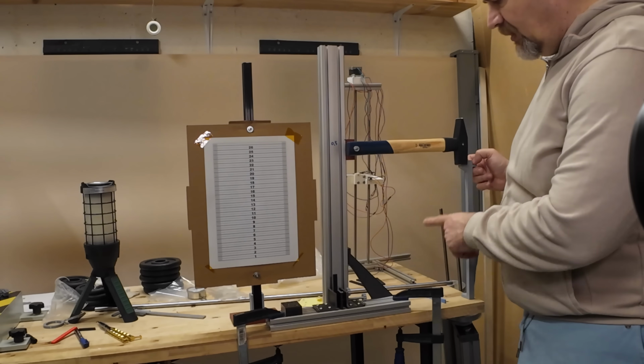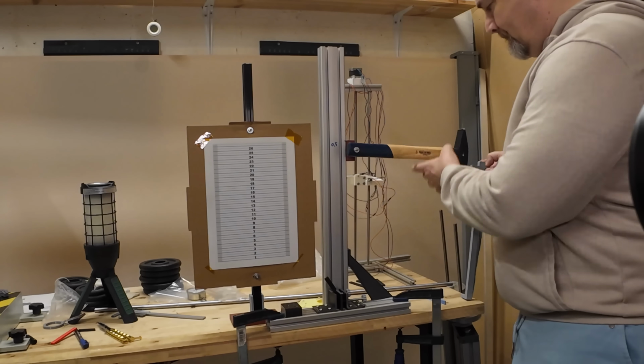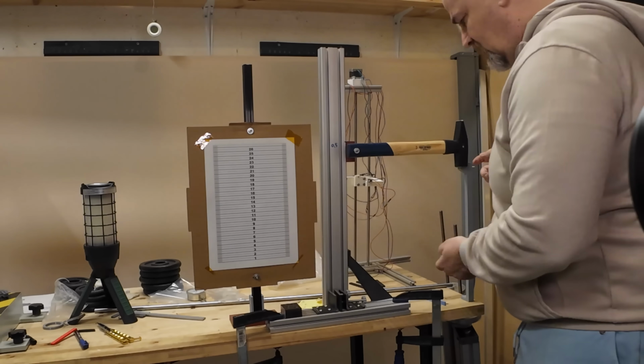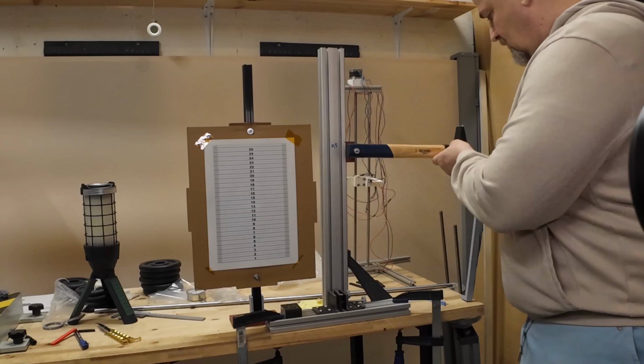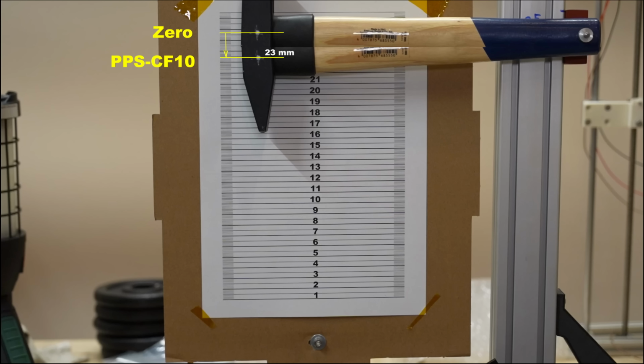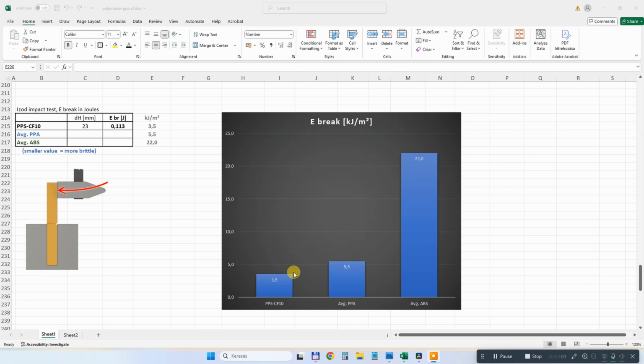Impact test with this half kilogram hammer. 0 position. From the 0 position, 23 mm is the edge position of the hammer, and from this I'm calculating the breaking energy, and this means that PPS is quite brittle material compared to the PPA, but of course compared to the ABS, and unfortunately this is very typical for the fiber reinforced filaments.